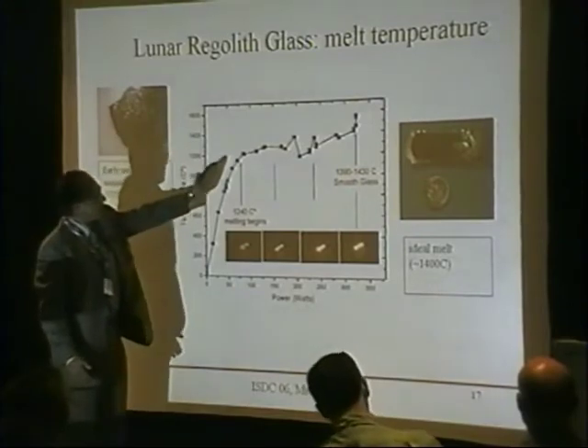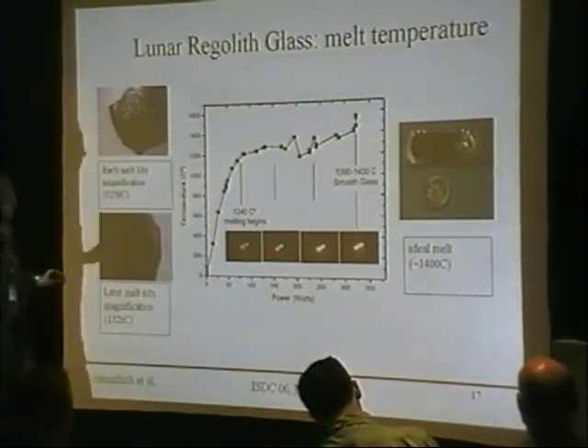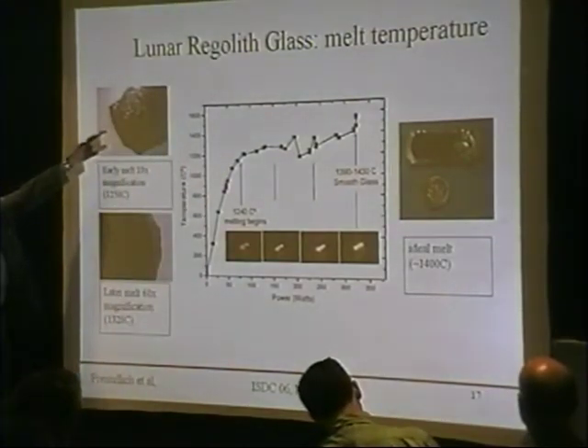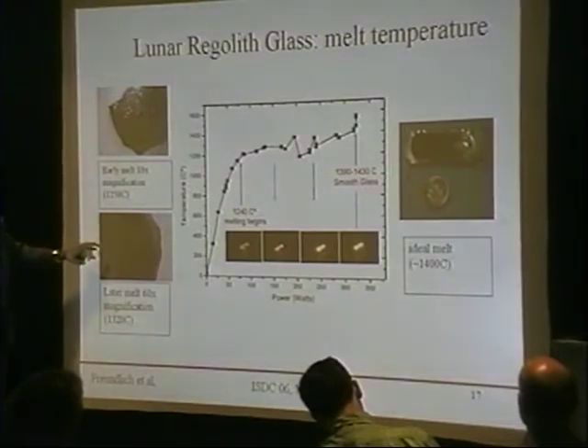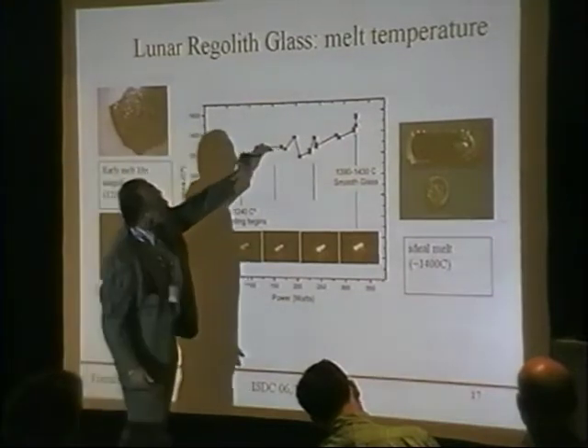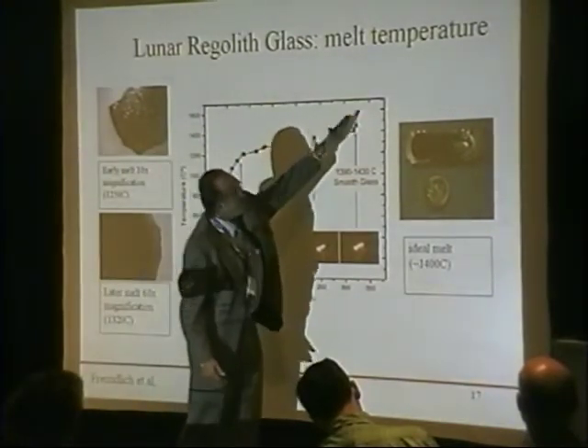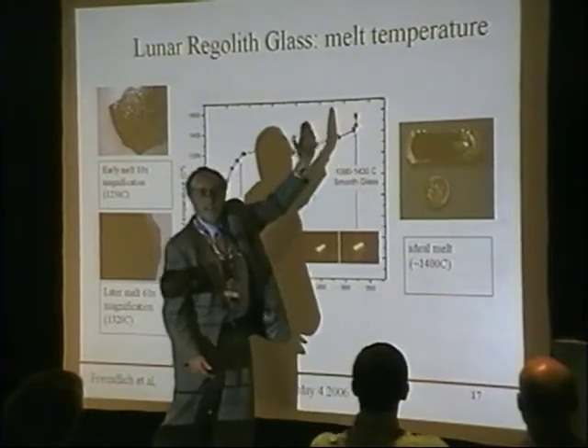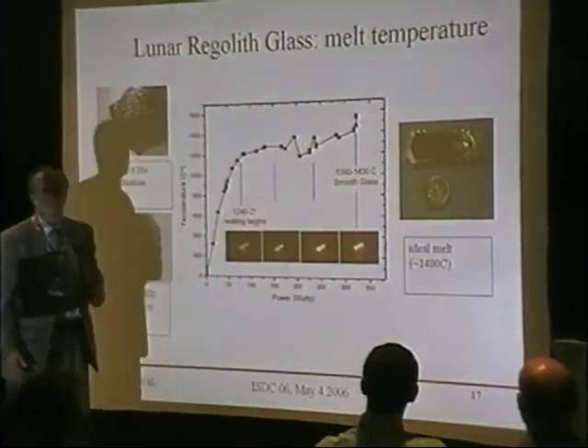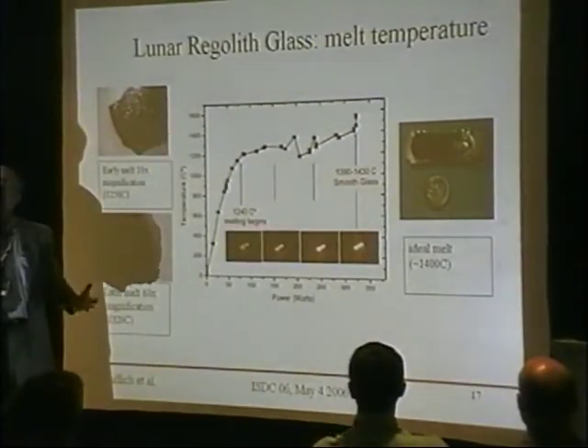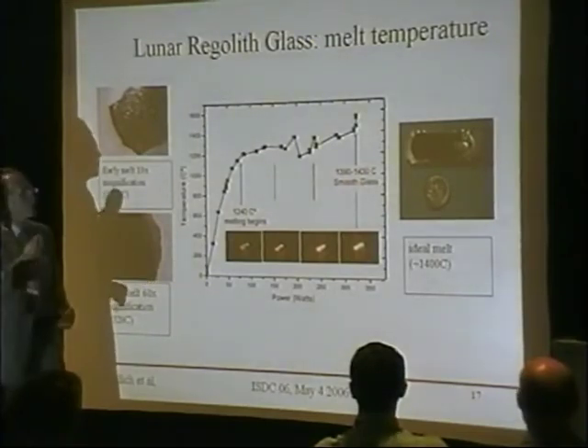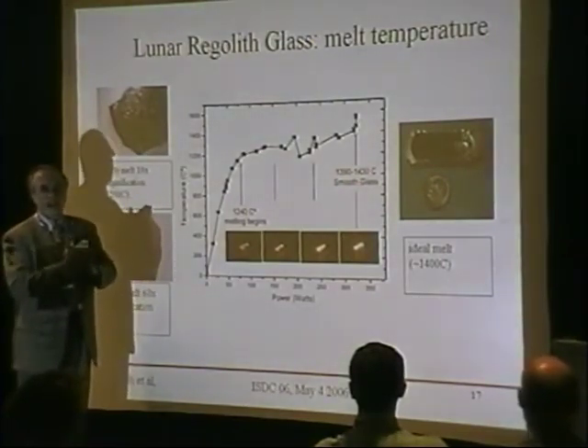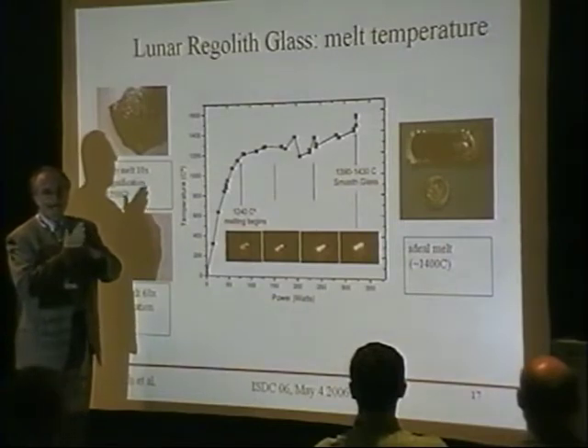We can stop the melt process early, but if it's stopped early, the product of the melt looks relatively uneven. And there's a good indicator here. You can see suddenly the temperature is starting to rise. That's a very good indication of a very strong change in the surface emissivity, and that's where you're getting to your absolute smoothness.